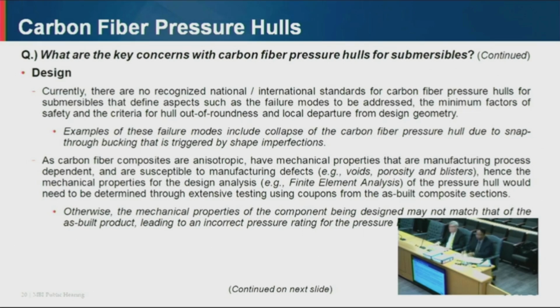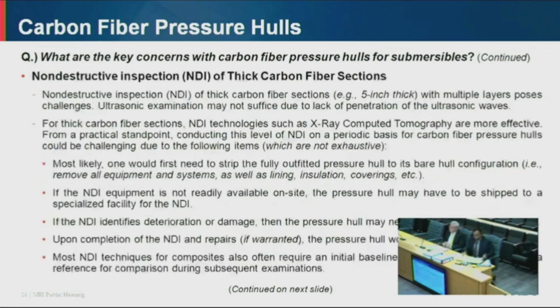Okay, next slide, please. So next we come to non-destructive inspection of thick carbon fiber sections. So if you have a very thick carbon fiber section, for example, a 5-inch thick section, ultrasonic examination may not be suitable because of lack of penetration of the ultrasonic waves and lack of reflection, okay? So using UT, you may not be able to evaluate thick carbon fiber composite sections.